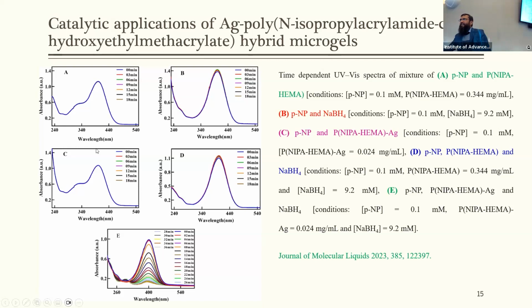We initially conducted some controlled experiments. The reduction of 4-nitrophenol was carried out in the presence of the pure microgel system, but no change in the absorbance or spectra of the p-nitrophenol was observed. In the second controlled experiment, we used sodium borohydride to reduce the p-nitrophenol, but sodium borohydride was not able to reduce the 4-nitrophenol into 4-aminophenol in the absence of core shell hybrid microgels.